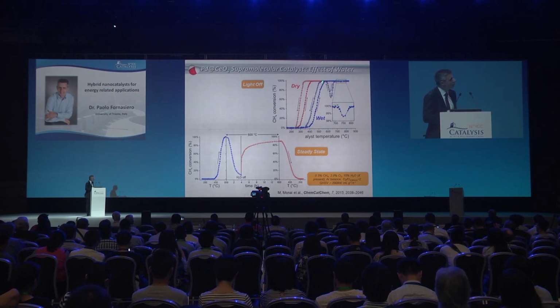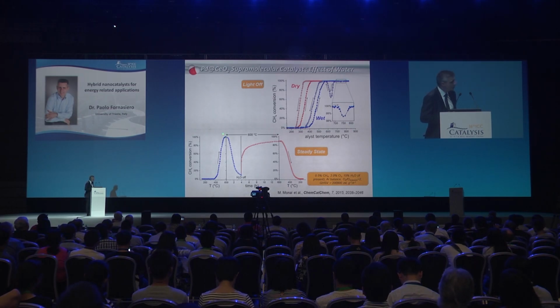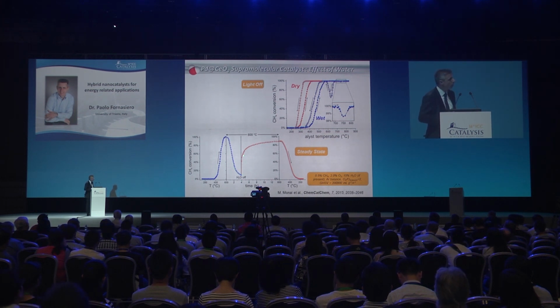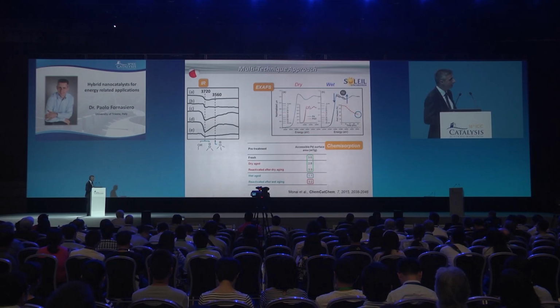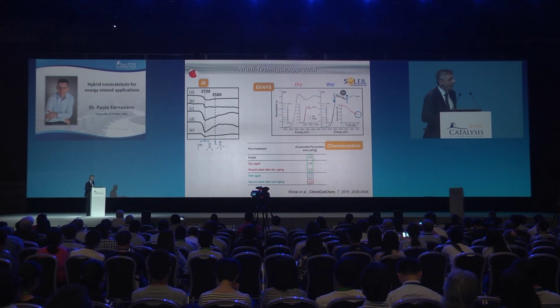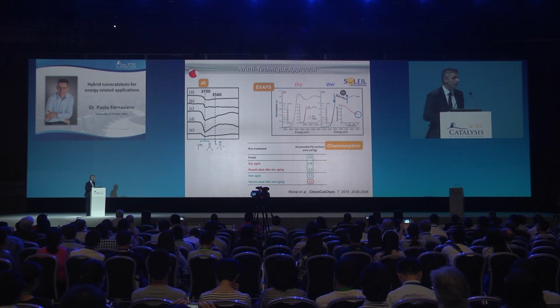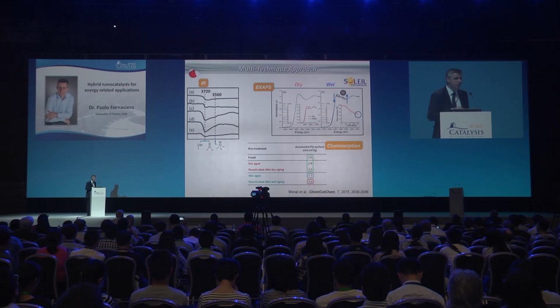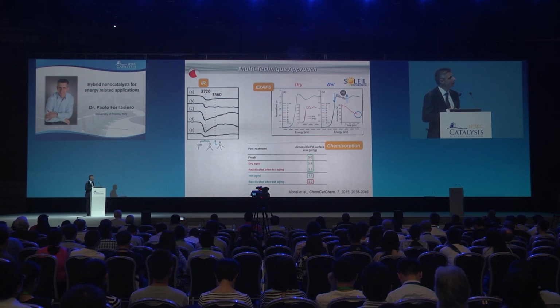So we were very much interested in understanding why we observed this deactivation. So we performed a steady-state experiment. You can see how quickly the catalyst is deactivated, completely killed in the presence of water. If you remove water at 600 degrees Celsius, you recover slowly and partially the activity, but still the catalyst is deactivated. And we did a lot of investigation to understand what's going on. Basically, we observed that we form stable OH groups in this catalyst, which are removed only by high temperature treatment. We did chemisorption measurements that proved that we reduce a little bit the accessible metal surface area, but not enough to explain the full deactivation of the catalyst.